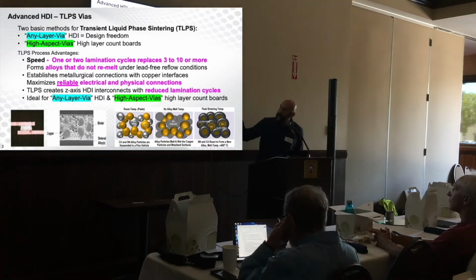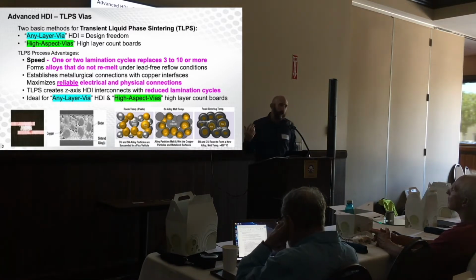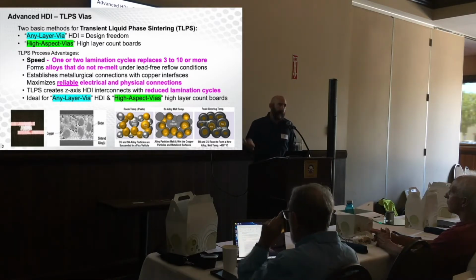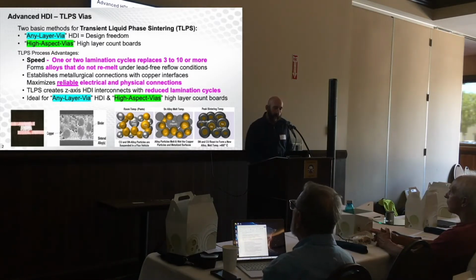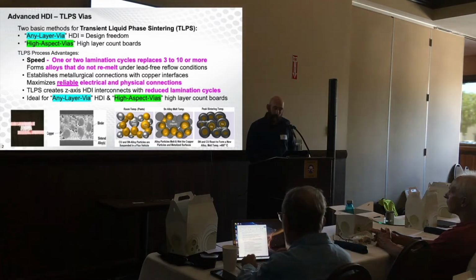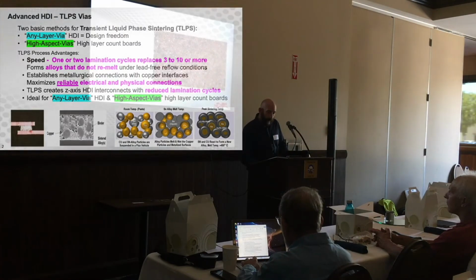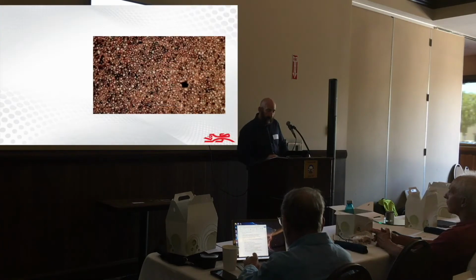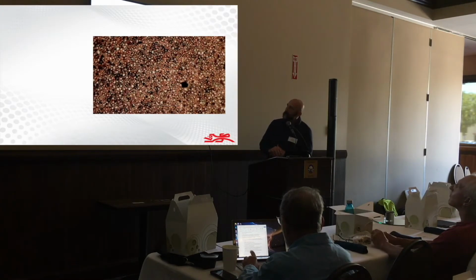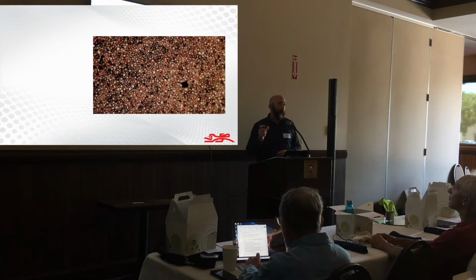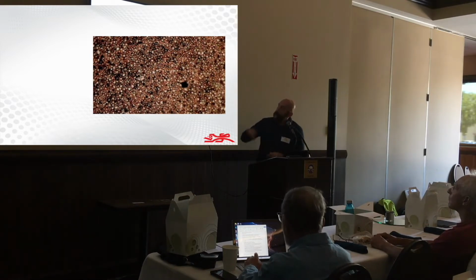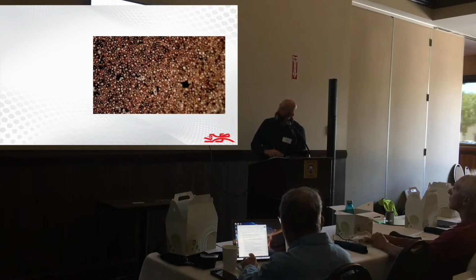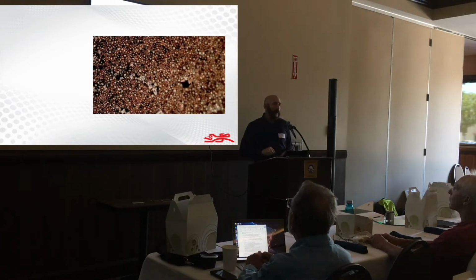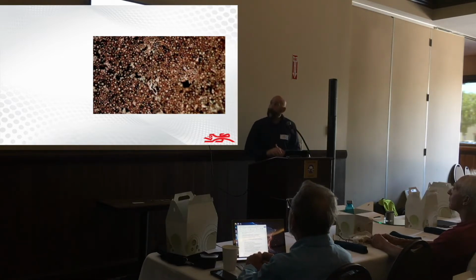So really it's a tin bismuth alloy that starts melting at 130 Celsius, and then at higher temperatures it starts kicking out the bismuth and forms an alloy with the copper. I got a little video of the paste sintering. This is a sample of the paste put between two glass slides and put on a hot plate under a microscope. You can see the copper particles, and then as the tin bismuth starts melting, it will react and combine with the copper.